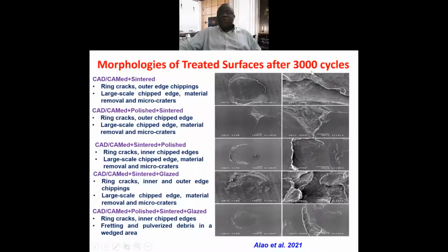Now, finally, at 3,000 cycles, you see the ring cracks. You can see the outer edge chippings. This one has now led to large-scale chipped edge, material removal, and micro craters. For the proposed manufacturing process, that is CAD-CAM polished sintered, you can see the ring cracks, outer chipped edge, large-scale chipped edge, and material removal and micro craters.